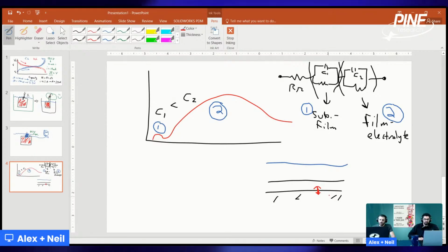Needless to say, the capacitance usually refers to the interface here, and the interfacial capacitance between two solid materials is usually pretty small. The interfacial capacitance between a liquid and a solid, this interface, is going to be larger. There's going to be a double layer, so you're going to have a bigger capacitive element there. And so typically the capacitance of the second arc is going to be bigger.